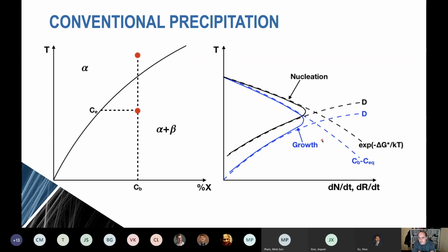So this compromise in choosing conditions for precipitation all comes about because we use a single state variable to control both mobility and driving force. We use the temperature. And so we started looking at this problem and say, well, what if you don't have to use temperature? What if you can create mobility in a different way and try to decouple, partially at least, the thermodynamics and the kinetics to try and control precipitation?